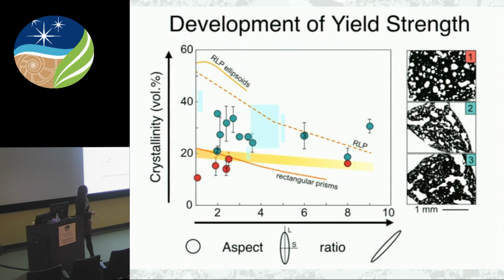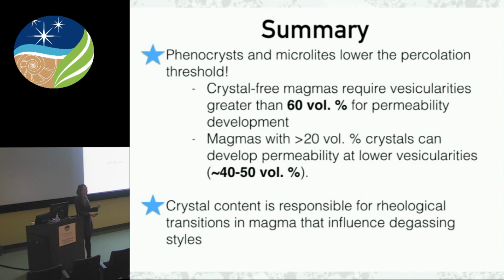And our data fit well with this lower threshold for rectangular prisms. The onset of random loose packing is really affected by the aspect ratio of the particles within the system. And typically, the higher the aspect ratio of the particles, the lower the threshold. We think the percolation threshold will not occur until very high vesicularities. Now, magmas with 20 volume percent crystals, or slightly higher, this will cause deformation of the bubbles and therefore lower the percolation threshold, maybe around 40 to 50 volume percent.